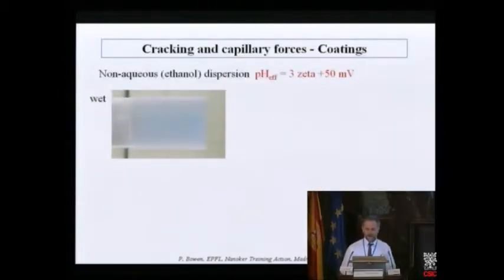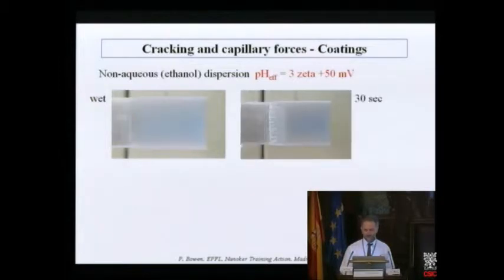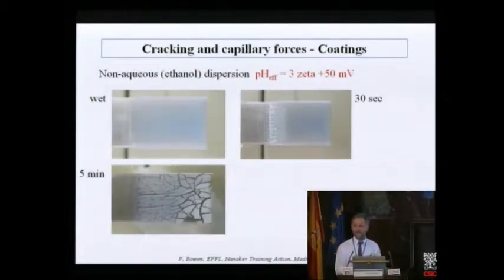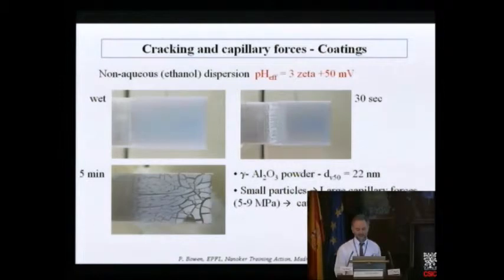If you take our gamma alumina, well milled, our Degussa, this is in ethanol. The zeta potential is modified, so we have good electrostatic dispersion. This is wet. This is after 30 seconds. This is after 5 minutes. Catastrophic cracking. So even reducing the surface tension using ethanol is often not enough for nano-sized particles. This is a gamma alumina with a dispersed particle size of 22 nanometers. So basically, it's very difficult to avoid.